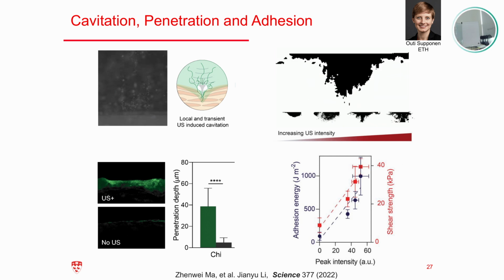So what's going on here? We tried to study the mechanism behind it. Here we have teamed up with a group at ETH, and we ended up with this proposal: the ultrasound is mainly doing cavitation, and when it cavitates the hydrogel solution, upon the collapse of the bubble, it will create microjetting. This microjetting will shoot preferentially toward the tissue substrate and enable the stapling or anchoring of this hydrogel polymer into the tissue. Following this hypothesis, we checked the penetration of this fluorescently labeled hydrogel polymer.